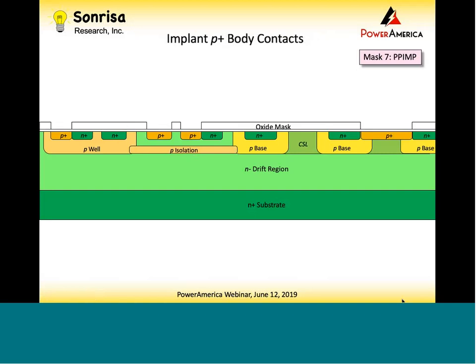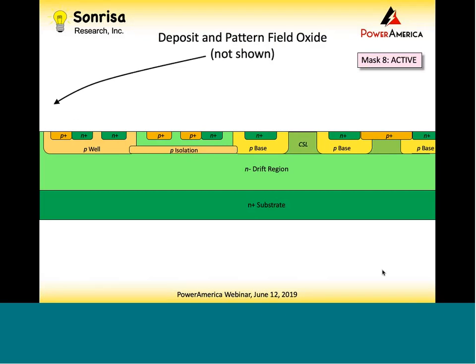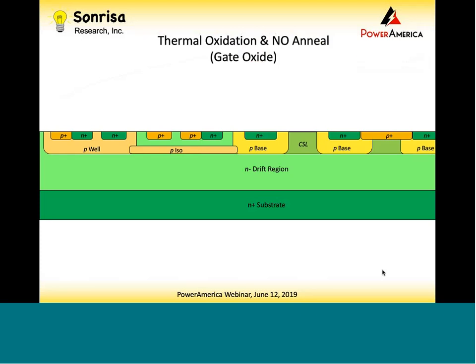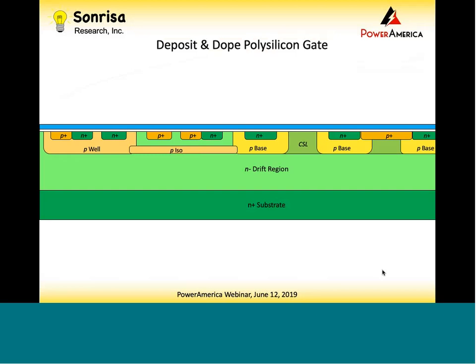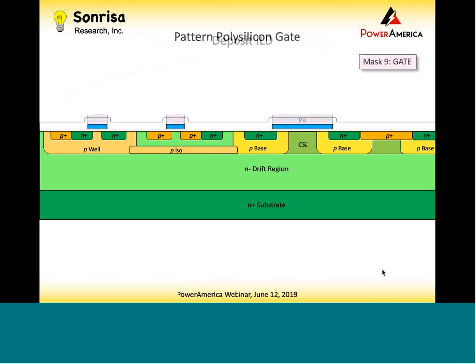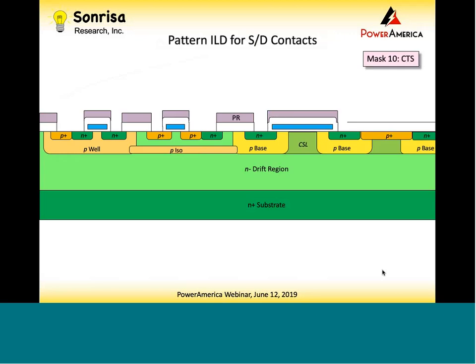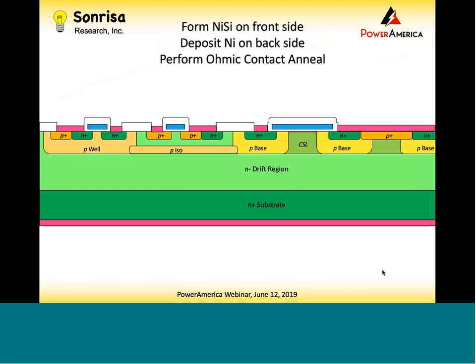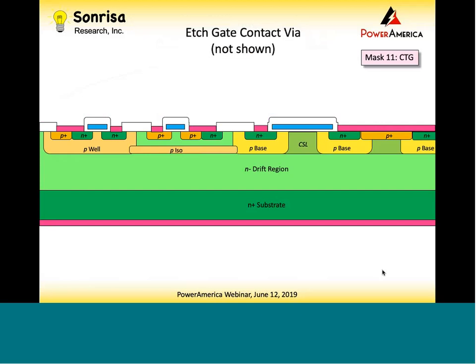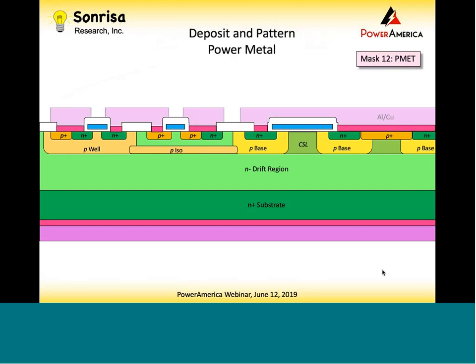We do the P-plus contacts. It gives us our base contacts for the DMOSFET, and it also is going to form the source and drain of our P-channel MOSFETs in the CMOS. We do a field oxide that's not shown here. We put down our gate oxide, we anneal that, we put down our gate, we dope it, we pattern the gate, we deposit an intermediate layer dielectric, we open windows in the dielectric, we deposit nickel silicide and form nickel silicide on the front and nickel on the back and do our ohmic contact anneals. We form our gate contact, that's not shown here, and then we put down our top metal and pattern that.